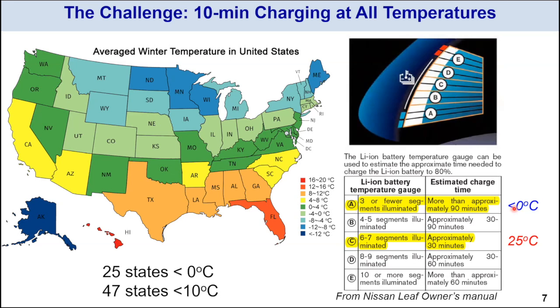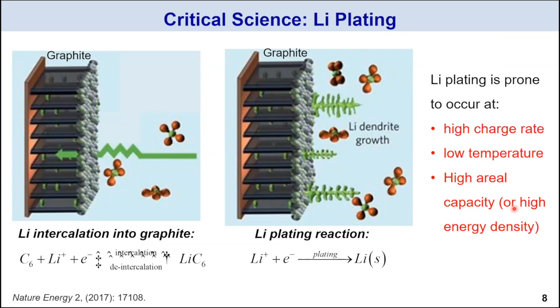So we need to find a technology that can do fast charging in Alaska throughout the year, as well as in Phoenix, right? And the scientific issue underlying fast charging is a phenomenon called lithium plating. So when I apply a very large current, you have a huge flux of lithium ions generated from the cathode, and they have to return into the anode, and so many ions don't have time to be nicely integrated into a graphite host. So instead, they would deposit as lithium metal on the surface of the graphite particle, and that is irreversible, causing capacity decay as well as a safety hazard.